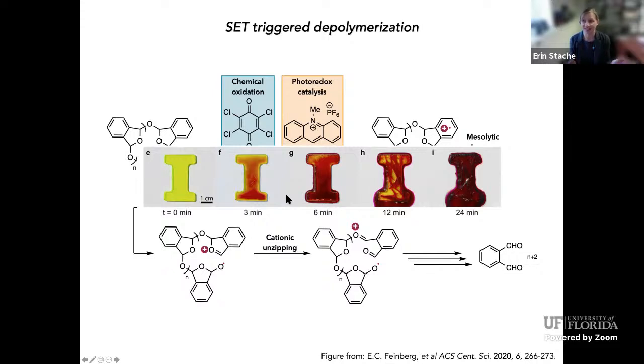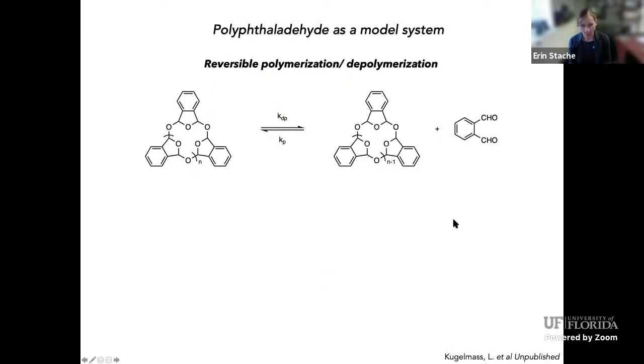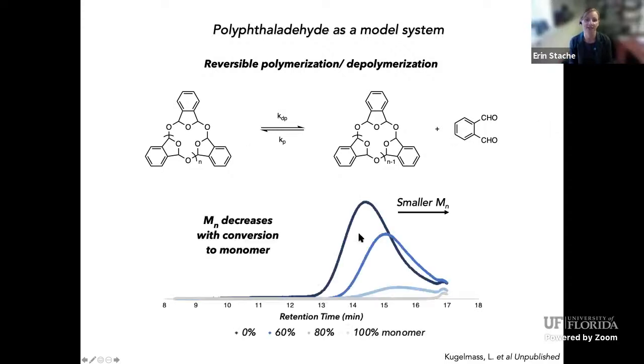But if they put it in sunlight, they can effect the same depolymerization in about the same time scale, actually. So it's a very efficient sunlight-mediated depolymerization. The way the depolymerization of polyphthalaldehyde works, I kind of just showed you, but with cyclic polyphthalaldehyde, it's thought that you can open up the cycle, extrude a monomer, and then it can actually close back up. So you might need to open and close it several times to get it to depolymerize.